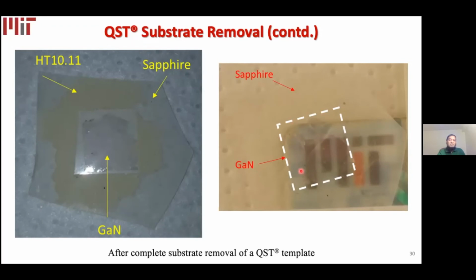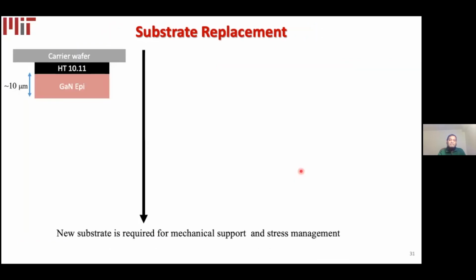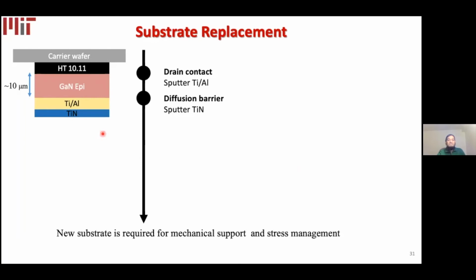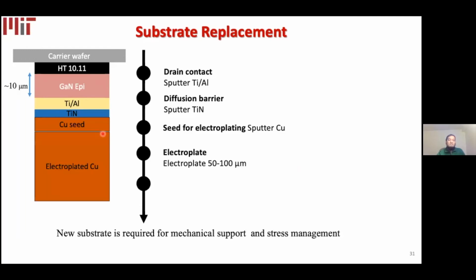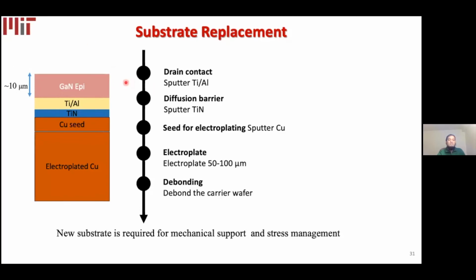So now that we have developed the substrate removal technology, the next step is to replace it so that we can debond the carrier and have a freestanding device. To do that, we start with our drain side contact, for which we typically use titanium aluminum. We sputter the drain contact on top of the N+ GaN, and then we use a diffusion barrier, titanium nitride. For electroplating, we deposit copper as the seed layer, and we electroplate 50 to 100 micron copper. Finally, we debond through the temporary bonding material, and we have our freestanding devices.